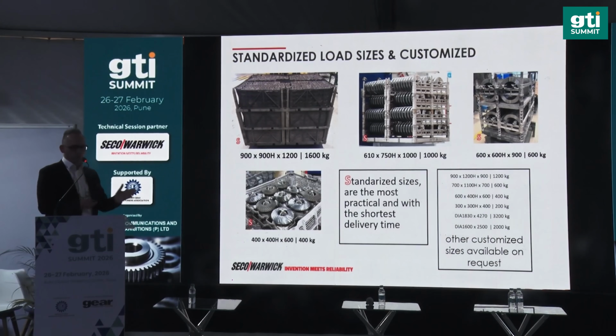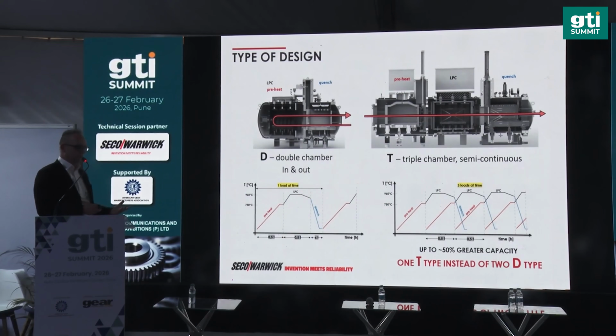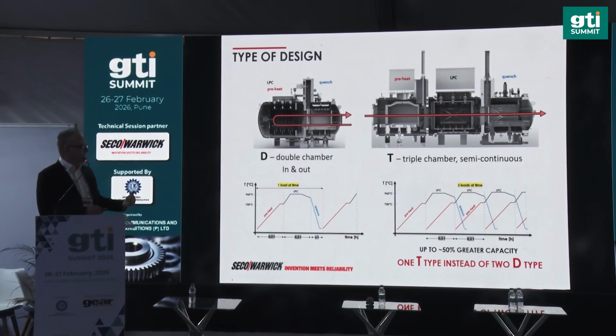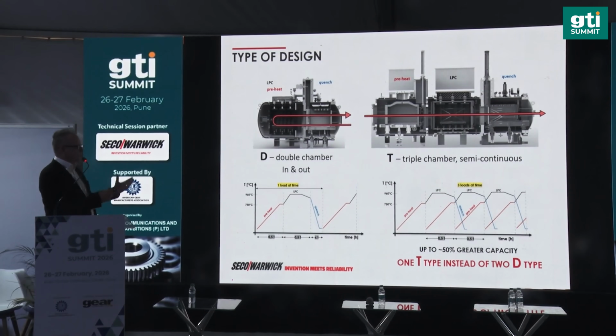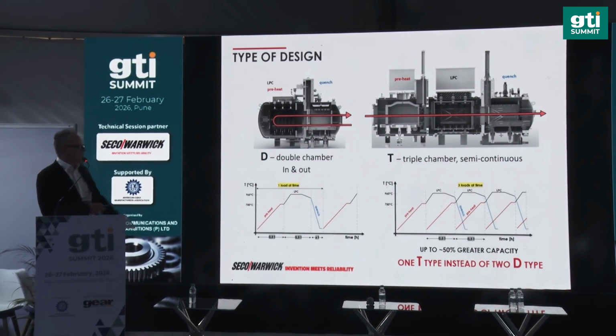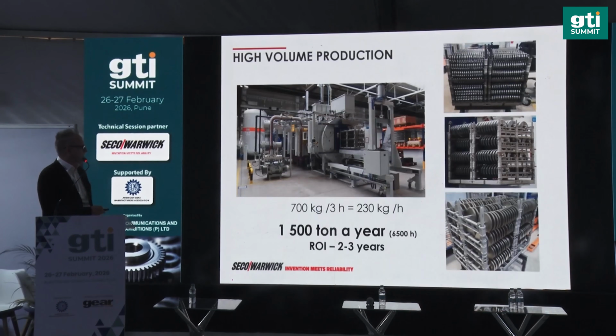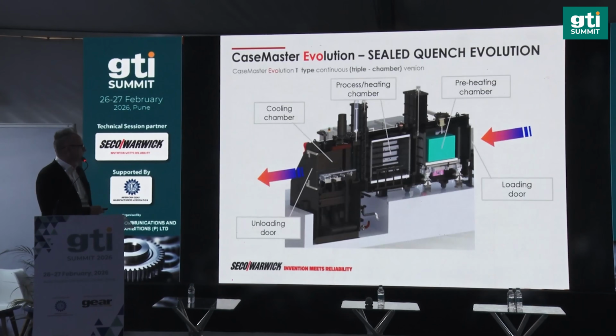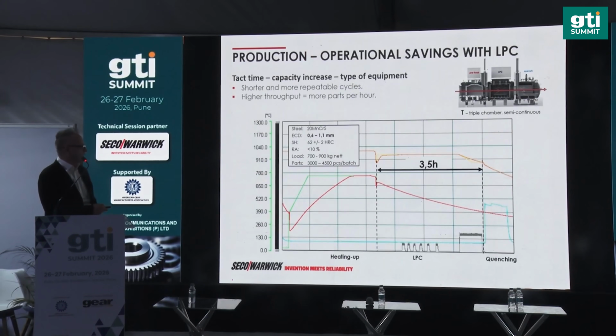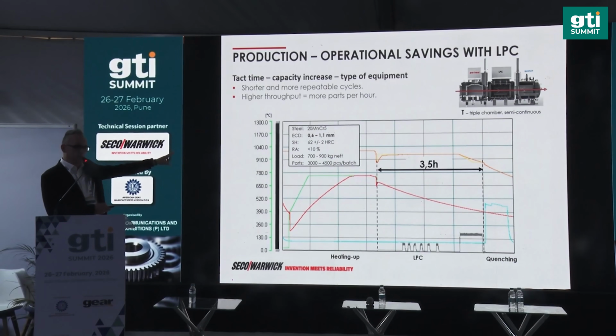Typical standard sizes, but of course if they cannot fit your portfolio, we may do customized ones. There are different approaches in the design of the equipment, especially aimed at increasing the throughput from the investment point of view. This solution in particular shows that in some cases one triple chamber furnace can replace two double chamber furnaces, giving you less investment cost at the very beginning and providing higher throughput capacity over the year. Of course, with high pressure gas quenching as well as oil quenching, in this particular case the triple chamber solution gives you a production takt time of 3.5 hours for 1 millimeter case depth.